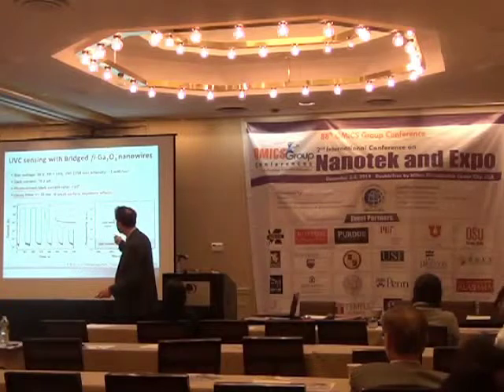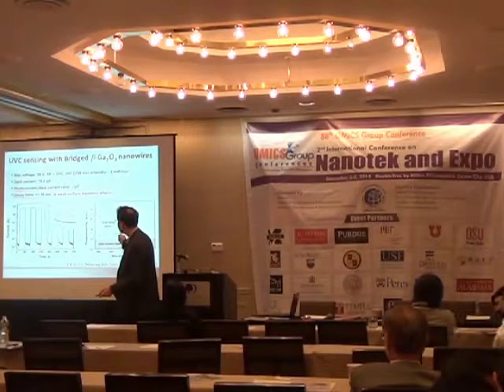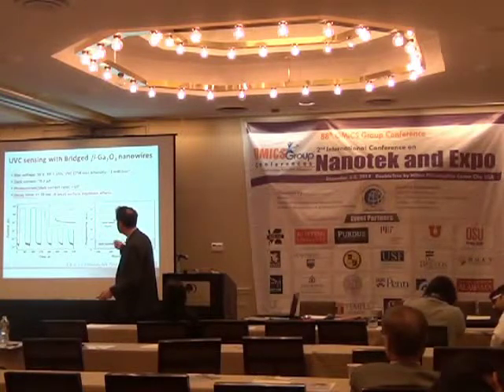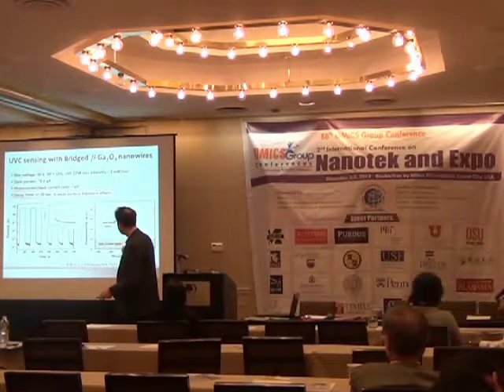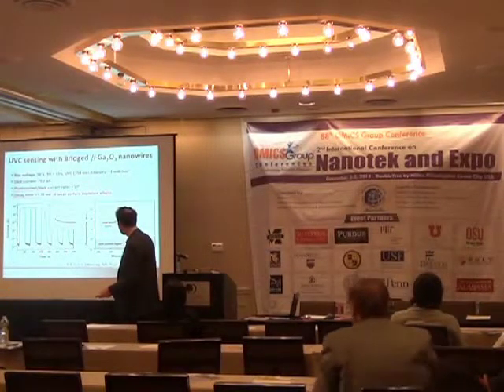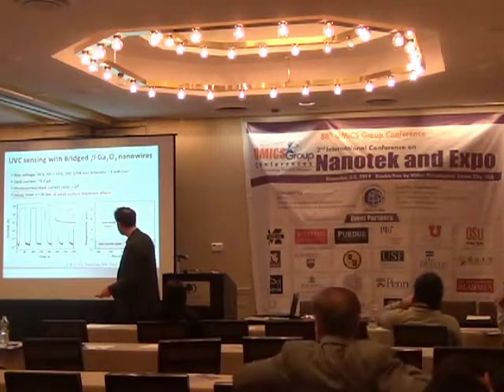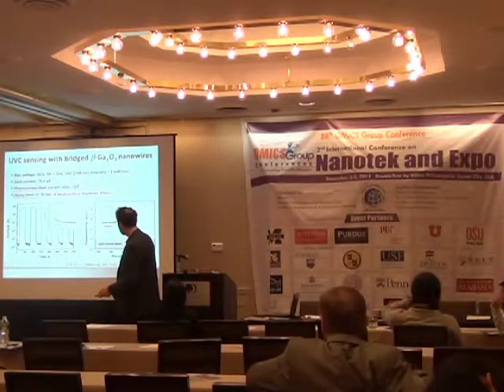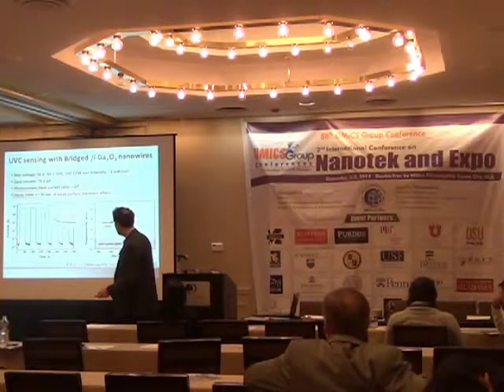We apply the same process with the gallium oxide, which is a very large band-gap material that is selective to deep UV. You can see the result here. So the material, gallium oxide here, is not sensitive to radiation above 280 nanometers. So this gives you a solar blind property.